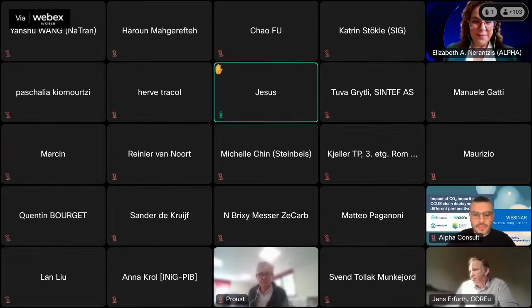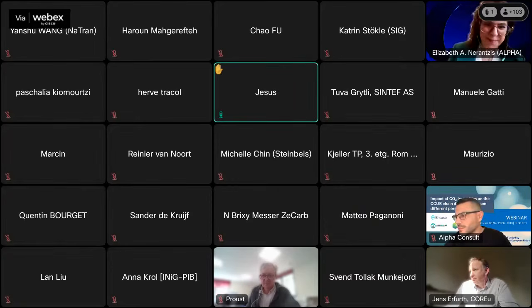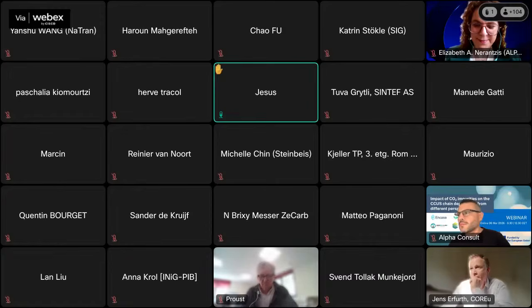Yeah, I may add on this issue. I agree with Jens that oxygen might be a concern for clogging by biofilm growth or whatever. In general, my impression is that the specifications for storage are much more lenient than for transport because I take for granted that we are going to use a high chromium stainless steel, because we work in high salinity. Once you mix the water with the CO2, you are going to have acidity. So the acidity of the CO2 itself, which would bring the pH down to 3 point something, together with the salinity, is highly corrosive.